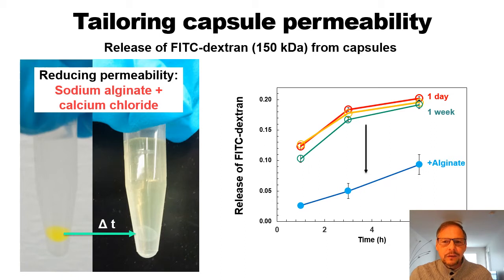In this case, we add alginate, which is a very important biopolymer. If we add alginate, you can see that the release of the material inside the capsule, which by the way was dextran, a dye, can be really reduced. So permeability can be quite nicely adjusted by adding other components in the biofilm formation.